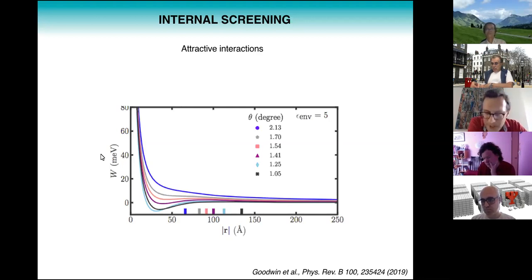It is in fact a different reason that gives rise to the attractive interactions. There is a discontinuity in k-space, but it doesn't derive from the Fermi distribution. It derives from the discontinuous behavior of the band velocity. What we know is that the band velocity is very strongly renormalized for low energy bands, but the high energy bands just have the unrenormalized graphene Fermi velocity. So it's this discontinuity of the band velocity that, when you Fourier transform it to real space, gives you attractive interactions.